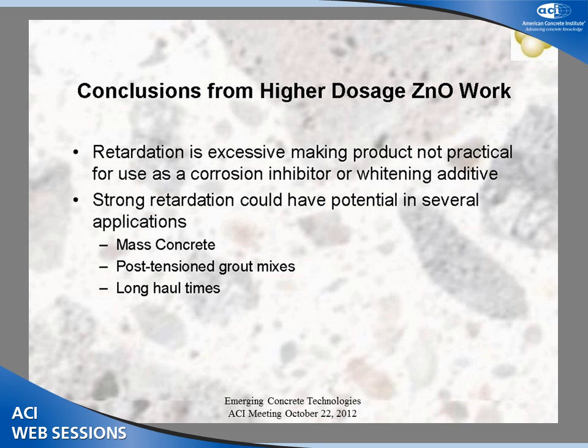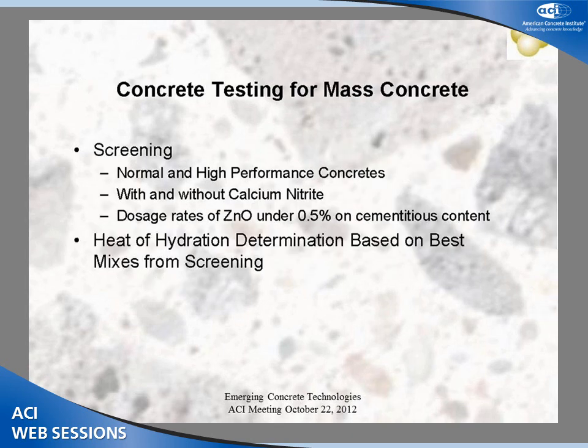So it is actually something that is very desirable to have in many different high-performance, high-quality concretes, such as high-strength concrete. The last thing that we want in a high-performance, high-strength mix would be for the hydration reaction to get out of control. We want to purposely control the hydration reaction. How do we typically do it as an industry these days? Well, through the use of conventional retarders. Years ago, all that we could do as an industry to slow down hydration was to cool the concrete. Years ago, and I'm going back 40, 50, 60 years and beyond, we didn't have chemical admixtures to slow down hydration, and so we had to physically cool the concrete with things like ice. But today we can control hydration chemically, independent of the temperature of the concrete, and so hydration control is a very important attribute in many different concretes.